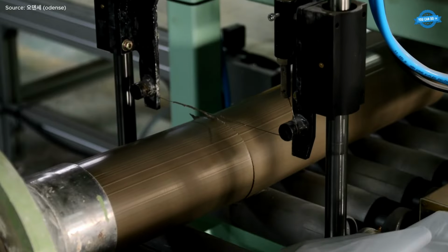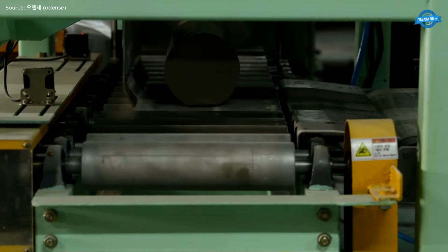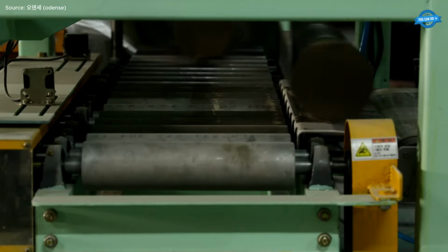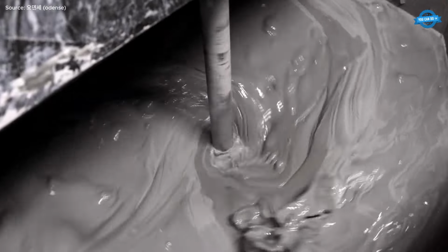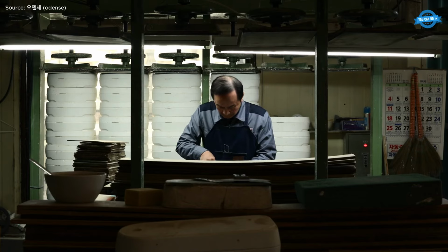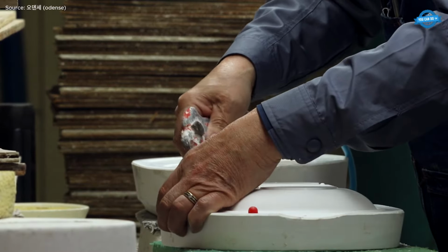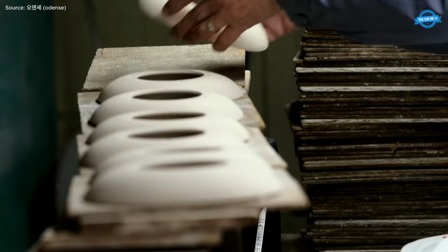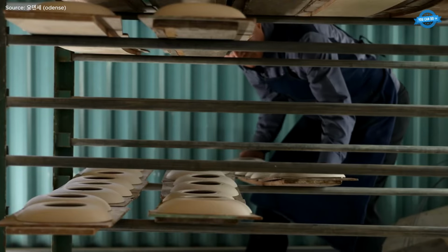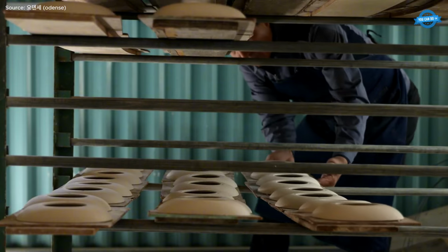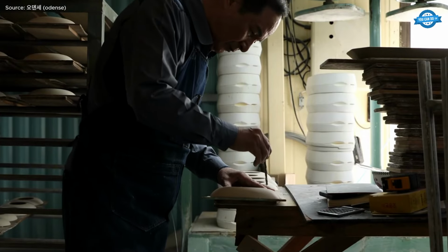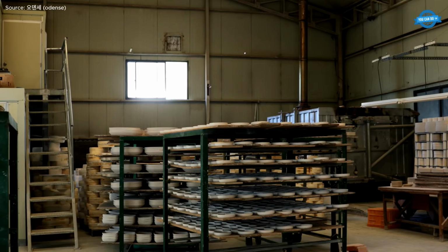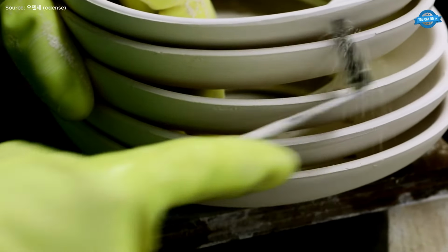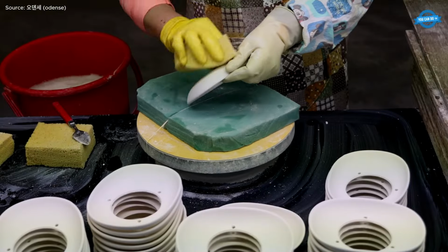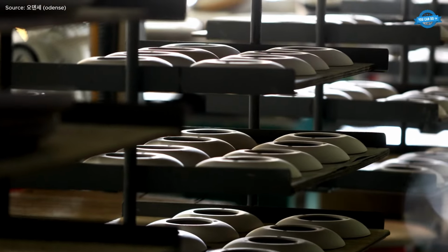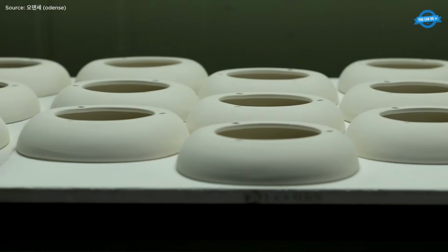Feldspar at 9% promotes vitrification, while silica sand at 13% ensures structural rigidity. Pottery stone, comprising 26%, provides body strength, complemented by clay at 15% for workability. Kaolin at 7% enhances thermal stability, and terra alba at 30% delivers a refined surface texture. These raw materials are carefully mixed, shaped, and fired to achieve dimensional accuracy and heat resistance suitable for lighting applications.